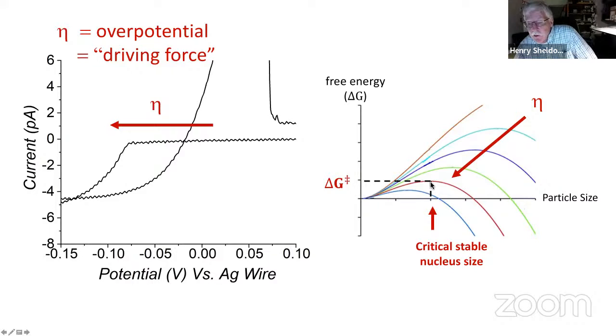And that activation energy, or this maximum in the free energy curve as the particle's growing, occurs because there are two contributions. There's a positive surface energy. You're creating a new surface, and that always costs you energy. But you're also creating a bulk material, and that's a negative contribution. And so when you sum those up, you get a maximum in this free energy curve. The maximum occurs at the critical and stable size of the nucleus.